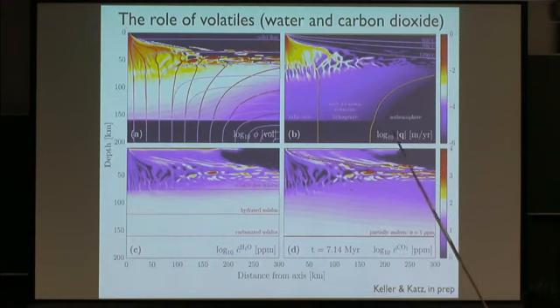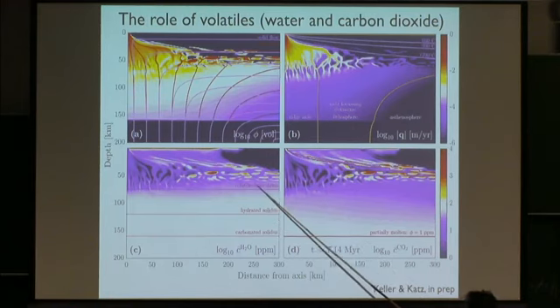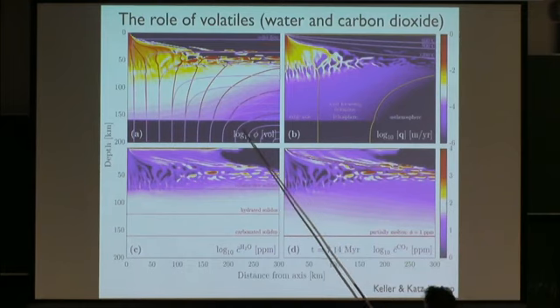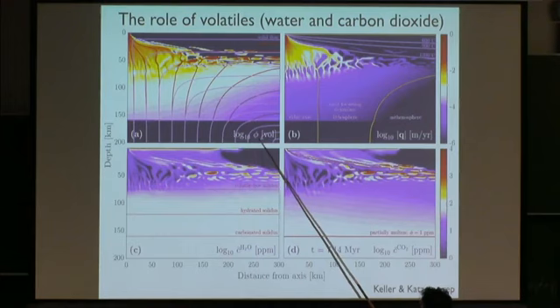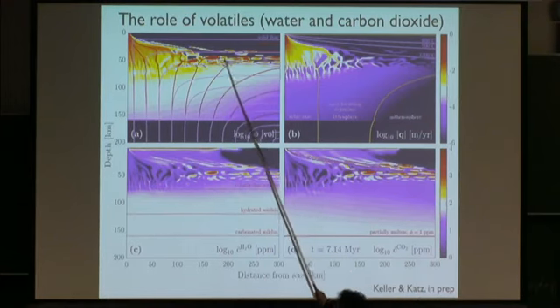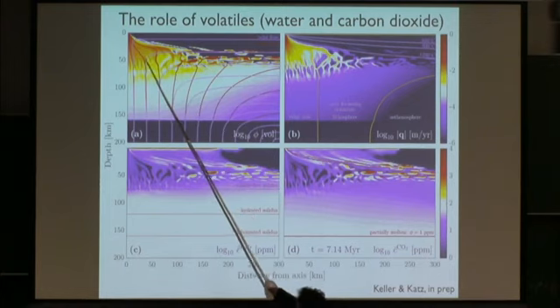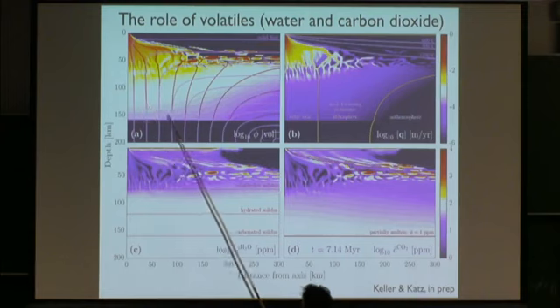Here we have a picture with water and carbon dioxide, the carbonated solidus, the hydrated solidus, and the volatile-free solidus. This is the log of porosity, and you can see massive variations. There's some pooled melt here, channels. The red lines are streamlines of the melt. Some melt gets to the ridge axis, some melt doesn't.